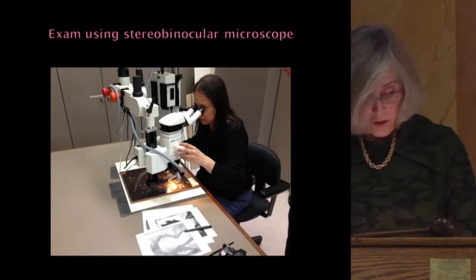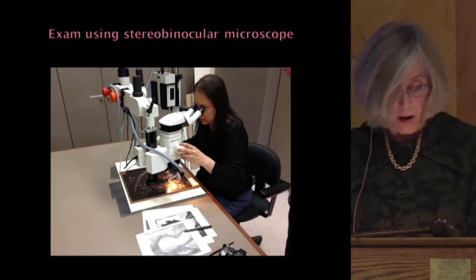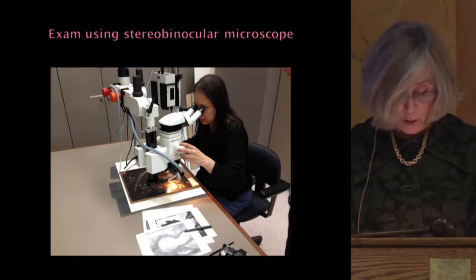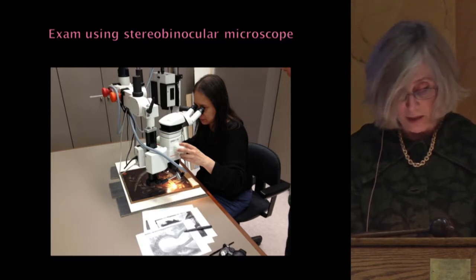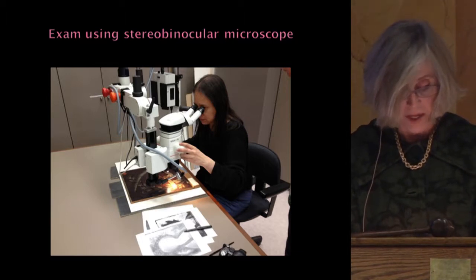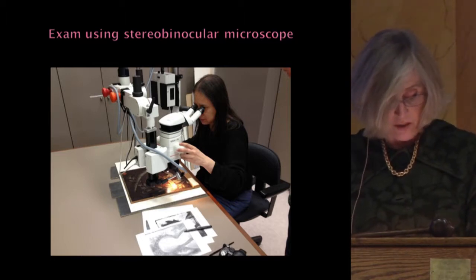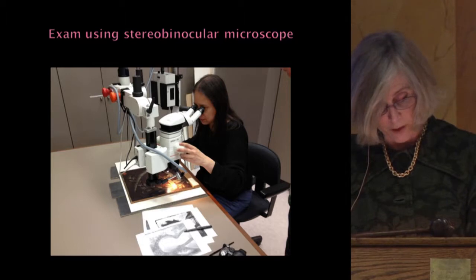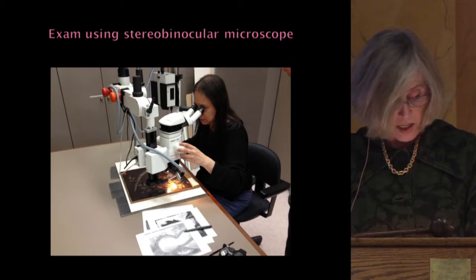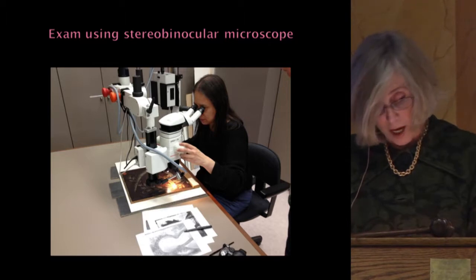Optical microscopy of the surface of a painting is an essential tool for the conservator in assessing condition, artist's technique, and for differentiating original from later restoration. Most conservators use low-power binocular microscopes to scan the paint surface, usually at 10 to 50 times magnification, before treating paintings. Under magnification, the conservator can distinguish original areas from repainted ones, since repaint typically spans cracks in the aged paint layer, while in areas of original paint, the cracking occurred years after the paint was applied, so no paint lies in the cracks.